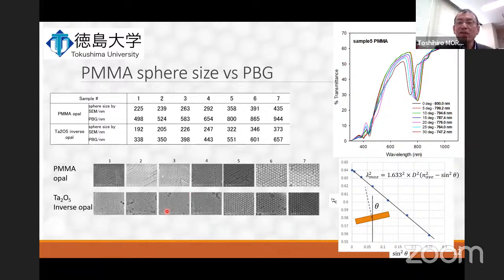Also, we estimate the photonic band gap wavelengths by using the modified Bragg equation from angle dependence. This is 0, 5, 10, 15, something like this. We change the incident angle and finally obtained the transmission spectra. When the incident angle changes, the absorption maximum shifts towards the shorter wavelengths like this. From the angle dependence of lambda max, to find the exact position of the photonic band gap using this equation, we can calculate here.